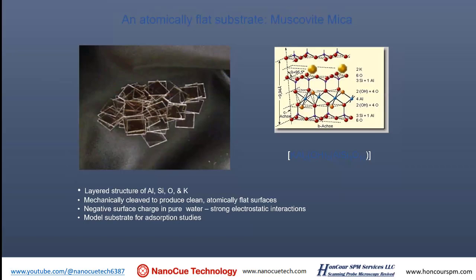The last presentation, which you can find on YouTube, was about how to prepare a lab. As I said in it, in case you don't remember, a good AFM lab always has a big collection of substrates. One is muscovite mica. It has a layered structure. It's an aluminum oxide and silicon oxide layered crystal, and between the layers there are no covalent bonds, only some potassium ions trapped between the layers. So if you apply a little bit of pressure between the layers, they will separate and expose the surface of the mica.